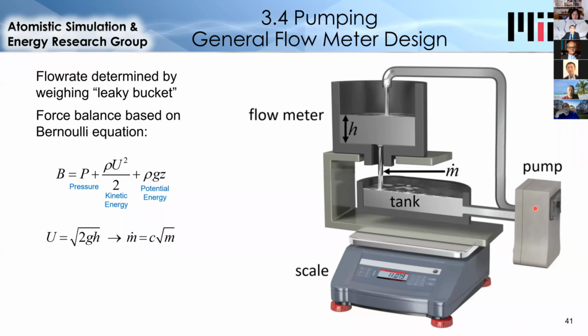And so when silicon or any fluid is pumped into the tank, it flows out of the bottom, but the height of the fluid in the tank is related to the incoming flow rate, because the faster the incoming flow rate is, the more pressure is needed to push the fluid out of the bottom of the tank. And this pressure comes from the gravitational pressure, which is related to the height of the fluid in the tank. This is well modeled by Bernoulli's equation, where the pressure is the same at the top and bottom surfaces because they're free. And so we're just comparing the velocity to the gravitational driving force. And so we can solve for velocity, which is proportional to the mass flow rate.